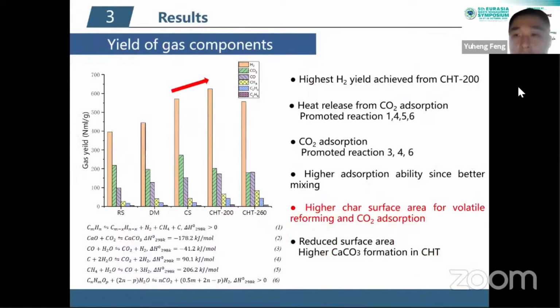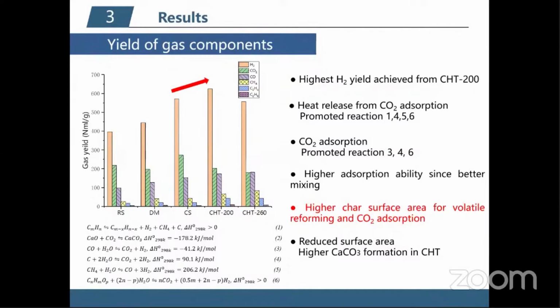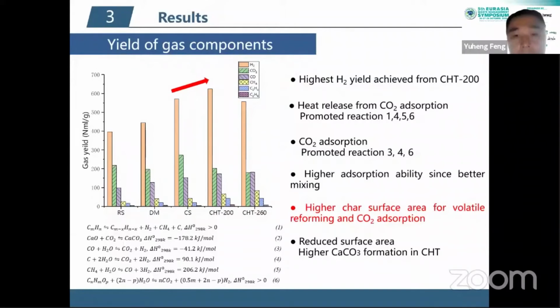I think in this research we did not change the ratio of calcium oxide, but in some other studies we adjusted the calcium oxide addition. I think it will depend on economic reasons, because when we add calcium oxide into the sludge, the heating value will be reduced. Above all, we found that 10% will be better than 20%, since it's just a compromise between the gas yield and the heating value of the gas. So I think 10% is better according to our research here.